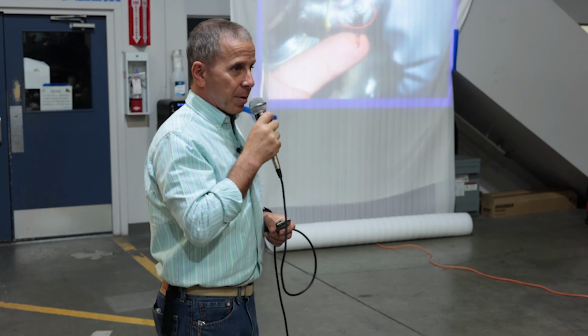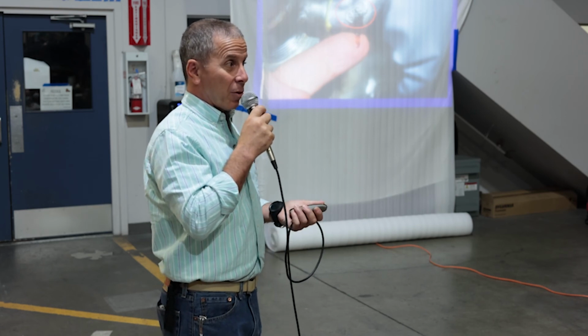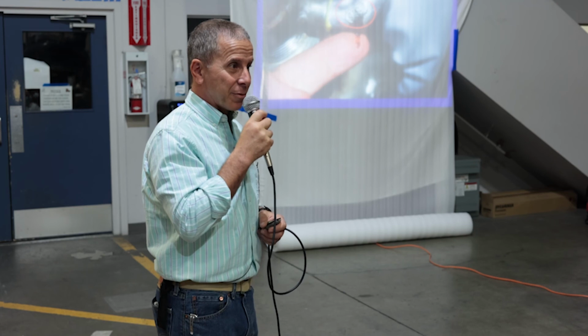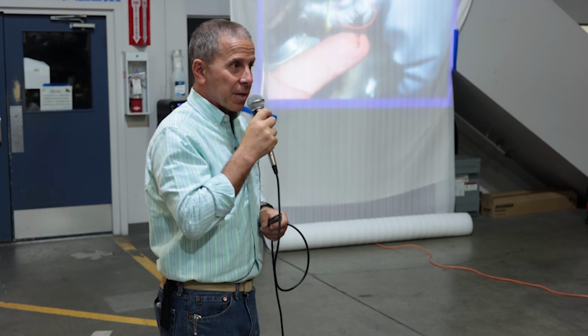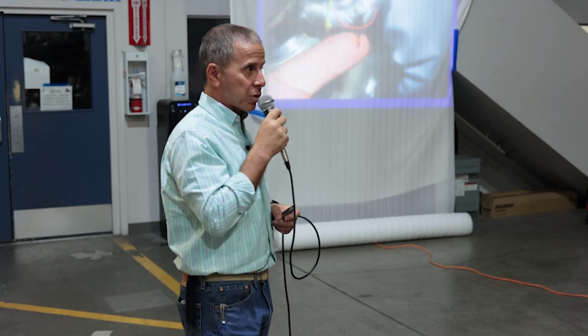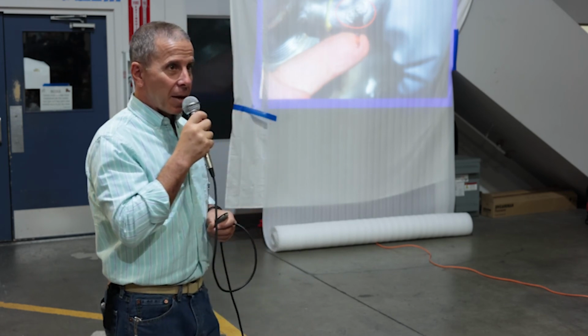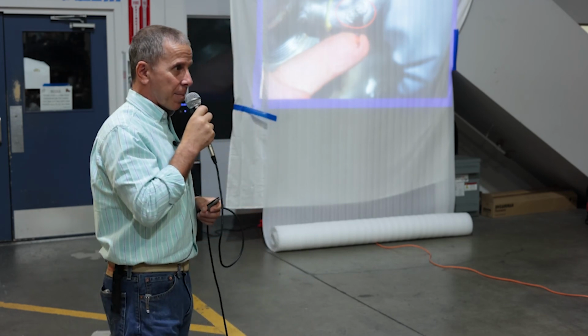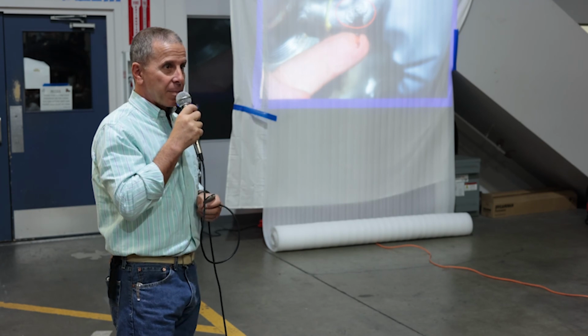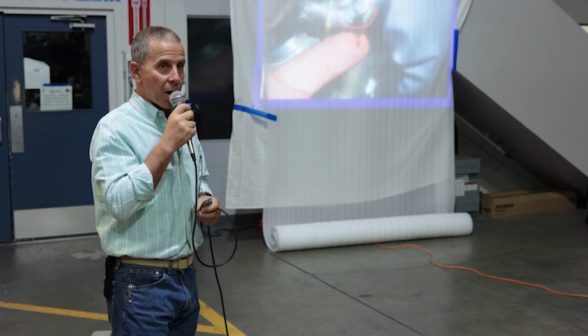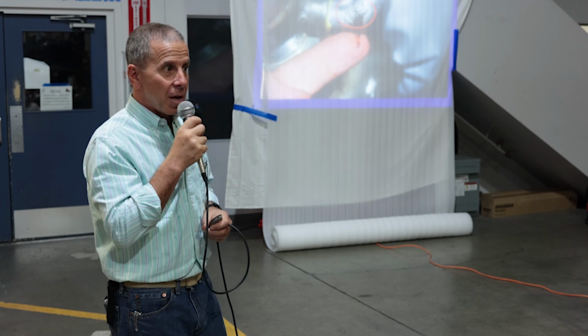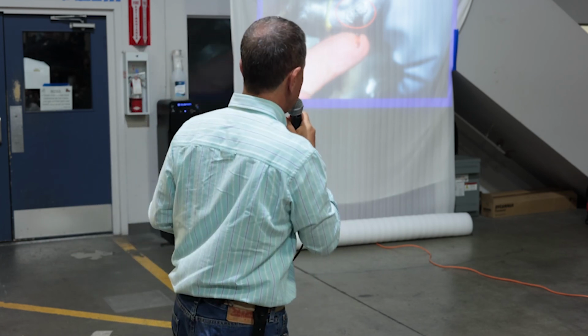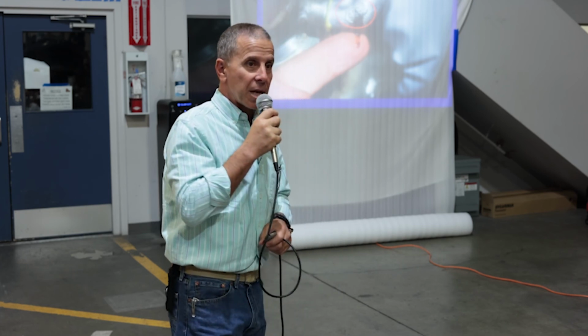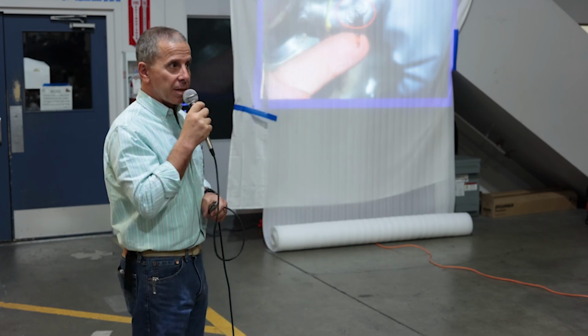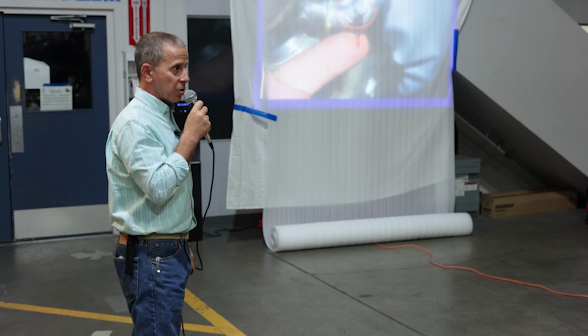If you're building an aluminum boat, you don't want to use copper alloys like bronze because that is harmful to the aluminum. And sometimes stainless is the next least worst scenario, and you're sort of stuck with it. It's just something that becomes a maintenance item. The people operating the boat need to be aware of the fact that the stainless steel could become active and crevice corrode. And again, that brown staining like that is the telltale, the warning that this has gone active and is corroding freely.